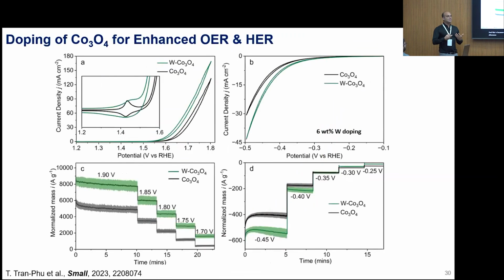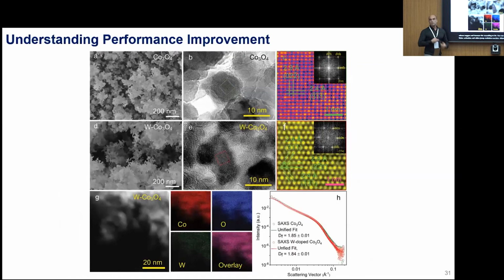So we try to modify this, and this is an example where we dope the same catalyst with tungsten. A little bit of tungsten, about 6%, shifts the onset potential, so where you basically start producing hydrogen, or in this case oxygen, from the water, and increases the current a lot. You can use it for both reactions, water oxidation and hydrogen evolution reaction. It works for both. And then we were trying to understand why this happens. Is it the surface?